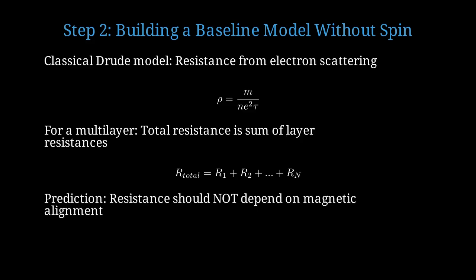For a multilayer stack, in the simplest approximation, the total resistance is just the sum of resistances from each layer. This assumes current flows perpendicular to the layers, which is called CPP geometry, for current perpendicular to plane. R total equals R1 plus R2 plus ... plus Rn. The key prediction of this baseline model is that resistance should not depend on the relative magnetic alignment of the layers. Magnetism doesn't enter the classical picture in any significant way.